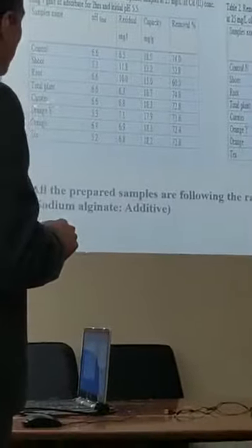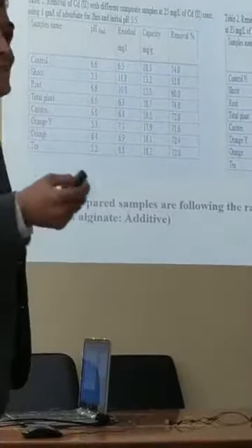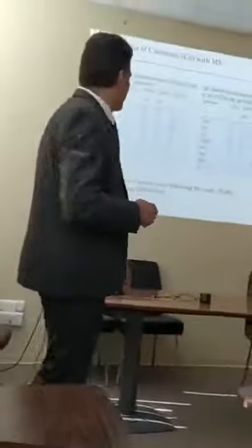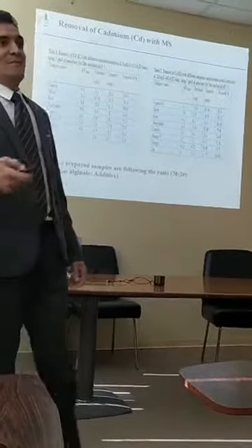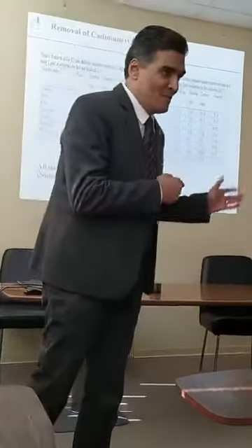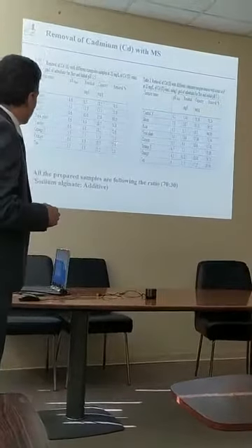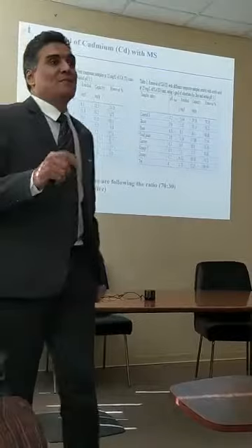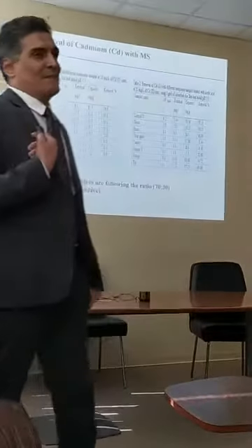And this is a control sample. This is shoot part of the water hyacinth plant, the root, the total plant, carrots plant, orange, and tea. Even the residue of tea could be produced in the form of microsphere, and even it has a rate of removal. It's not so high, but it's not bad also. By the way, it works within 2 hours, not half an hour like our starting results.